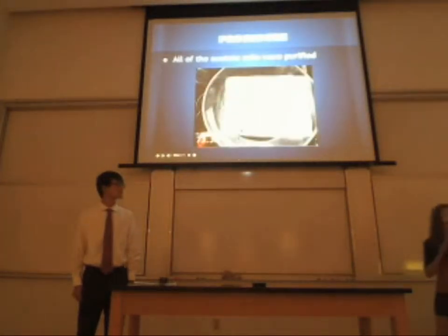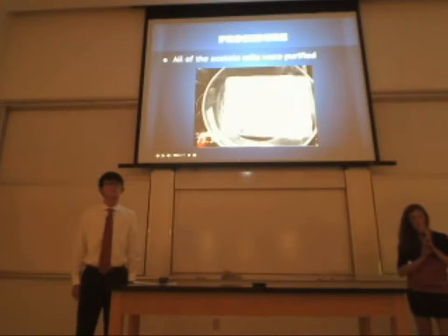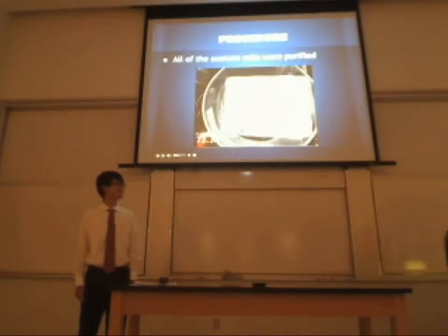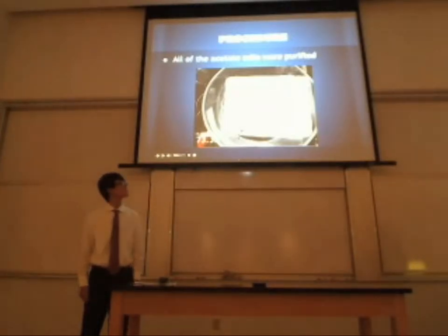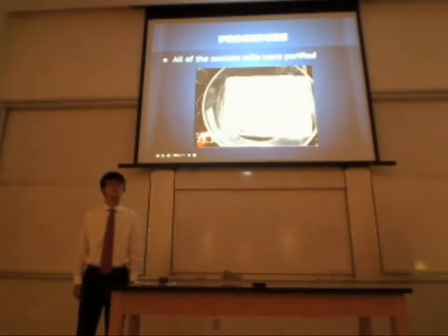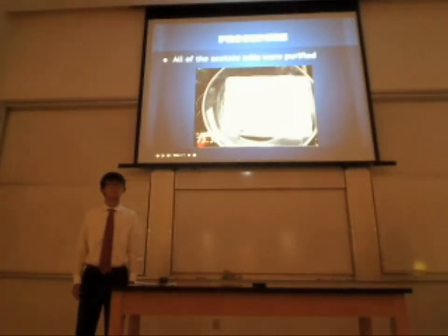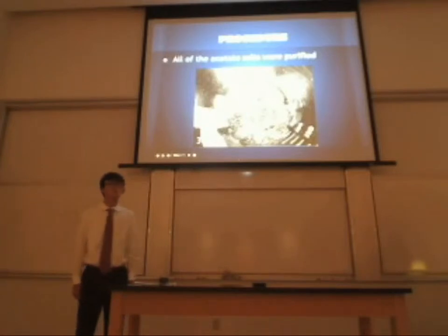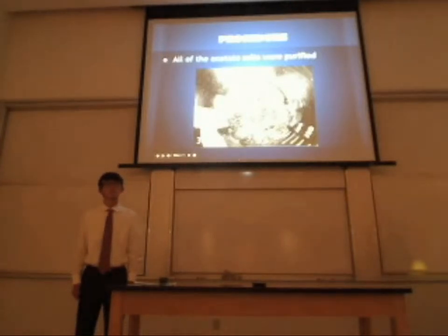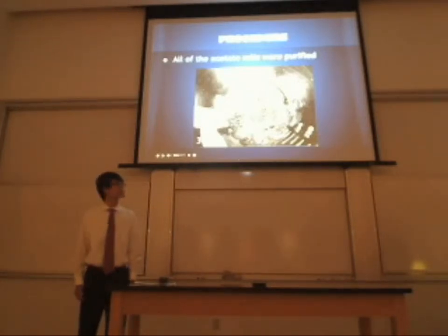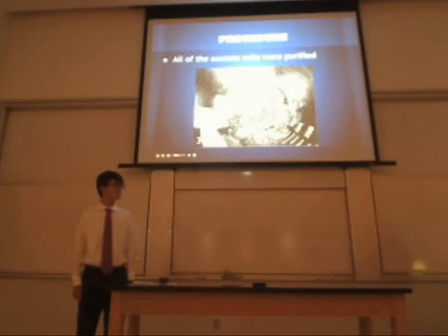For the zinc, crystallizing zinc was sort of like climbing Mount Everest for us. It's really hard, but once you get there, it's really cool. For our first zinc experiment, we got a 73.3% yield, and the crystals were in a needle-like structure. For our second, we got zinc crystals with a 39.86% yield and polygonal structure. We are assuming the reason for this difference in structures is the different amount of water contained in the crystal lattices.